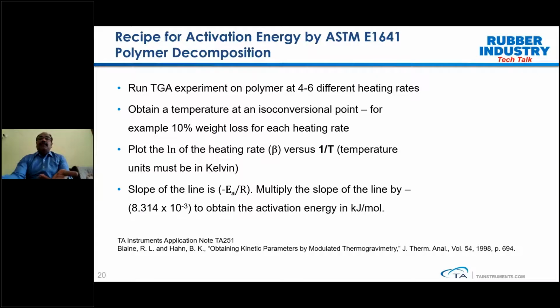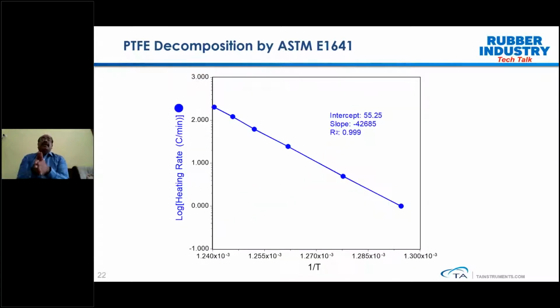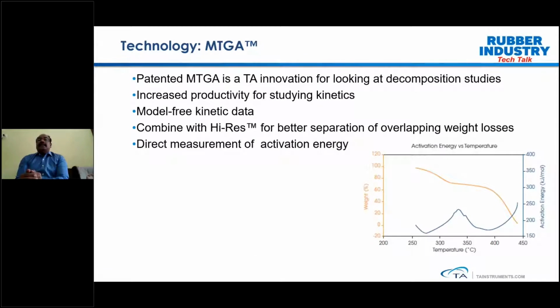Okay, but now you don't need to do this kind of study. The benefit is we have a technique called modulated TGA. The idea is how you can do this study, understanding of polymer decomposition kinetics, by a single run. As I explained, the normal ASTM technique involves multiple heating cycles, whereas in this case we don't want to perform multiple. In a single heating cycle, you would be able to calculate the activation energy. So that is called modulated TGA.